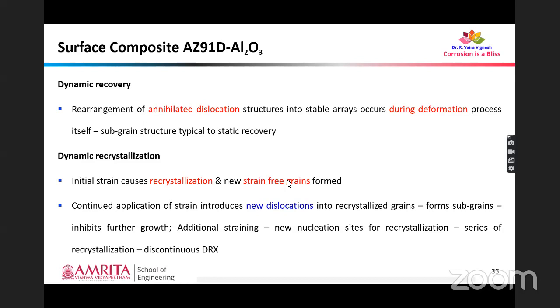So if we have continued application of strain, that will result in introduction of new dislocations into the recrystallized grains. So they will form subgrains again, and this will inhibit their further growth. This additional straining and formation of new nucleation sites for recrystallization is called a series of recrystallization, which is also called the discontinuous dynamic recrystallization phenomenon. So this also happens in FSP. This cumulatively adds up strength towards the microstructural evolution during friction stir processing of magnesium.